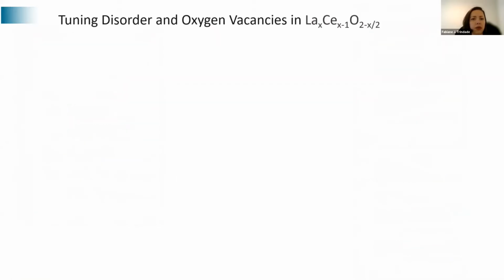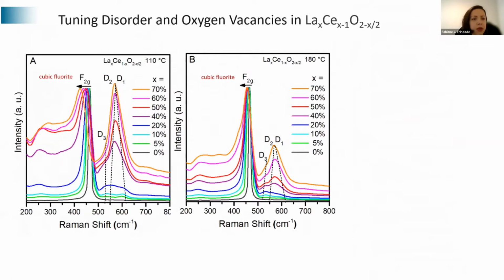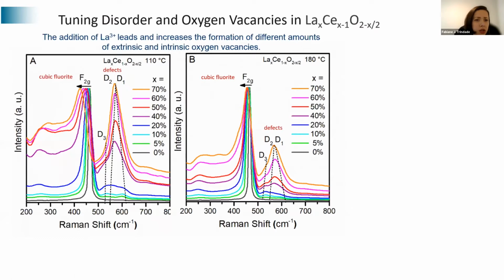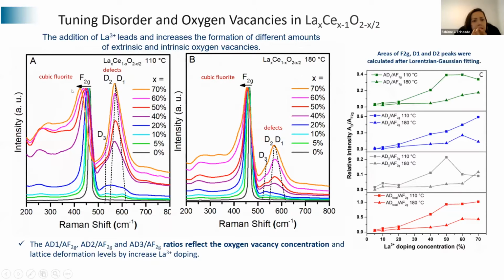So here in the Raman measurements, we will see this effect very clearly. As I said, the cubic fluorite structure is essentially maintained. The F2G peak is a peak for the Ceria materials, and then this peak is shifted to lower wavenumbers, and then we see here also the